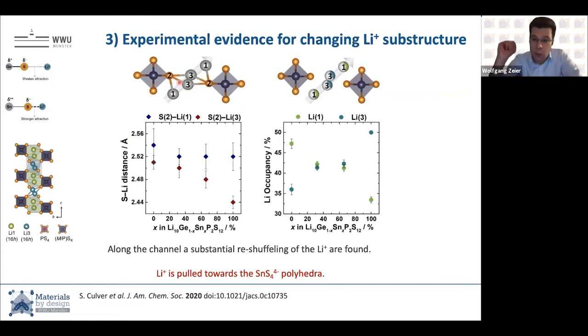And so we took temperature-dependent neutron data, refined and looked at the different distances that we get. The error bars are averages over all of the temperature data, to get an idea how reliable these changes are. What we see in blue is that the distance of the sulfur 2 and the lithium 1 doesn't change much from germanium to tin.